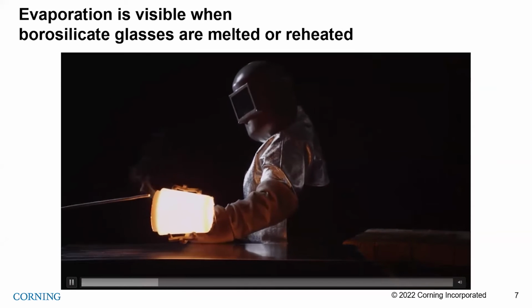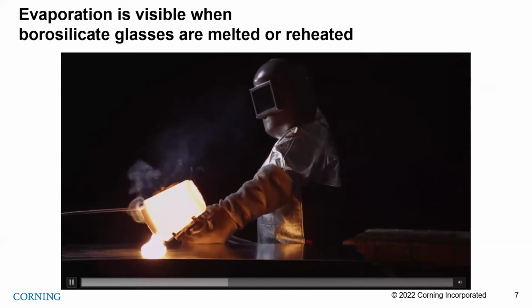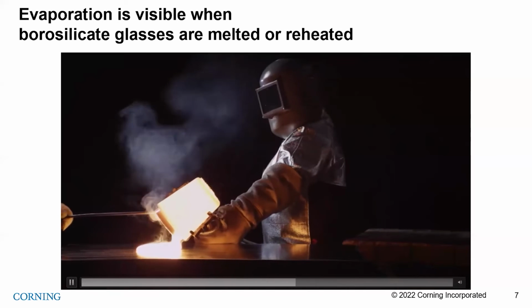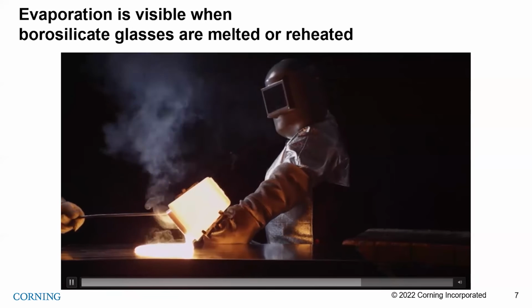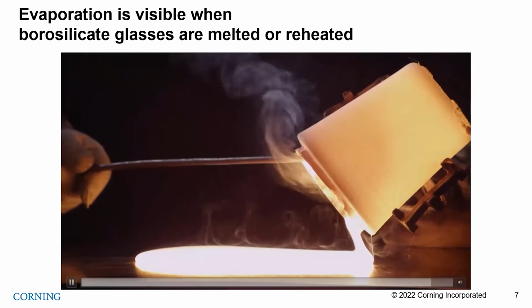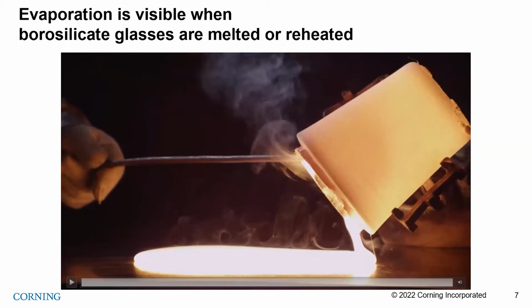This phenomenon is really obvious whenever we melt and form these glasses. Borosilicate glasses are known to evaporate sodium and boron. All of that material that you see leaving the surface is sodium and boron. And every time you stretch that surface or reheat it, there's going to be more material evolved from the surface.